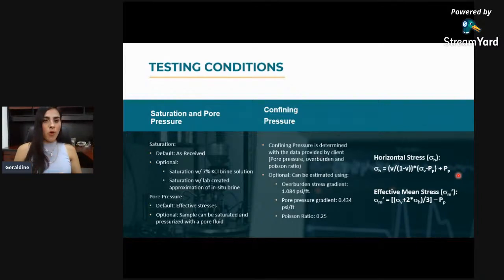What about saturation and pore pressure of the sample? Well, normally, by standard, samples are run as received. What this means is we don't saturate the sample with any fluid because, as I said, we keep it in refrigeration until the testing moment in order to keep the natural fluid saturation. But optionally, if the client or the person requesting the test requires it, the sample can also be saturated with a solution of KCl at 7%, or even with any brine that they require, and we can create it in the laboratory.